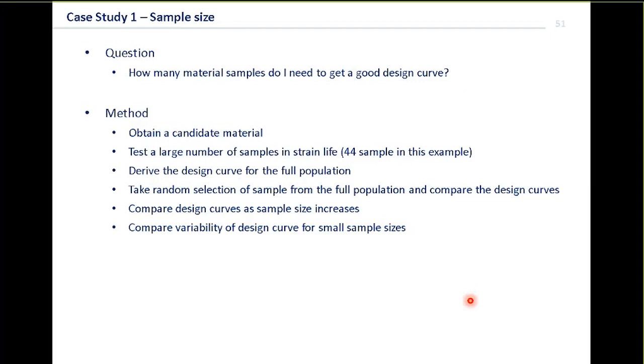So in this experiment, what we do is we've obtained a candidate material, a very common mild steel in this case. We've tested a very large number of samples, in this case 44 samples. And we've derived a design curve for that full population. We've then taken several random selections from that full population and compared it with the design curve. And what we're trying to do is to find a point when the design curve becomes economically optimum, i.e. adding more points doesn't improve it any, but if we drop points, then the safety factor becomes large.